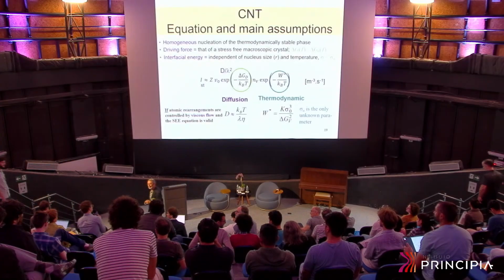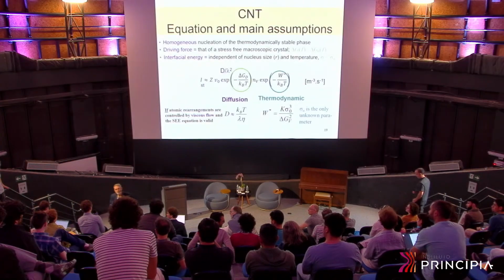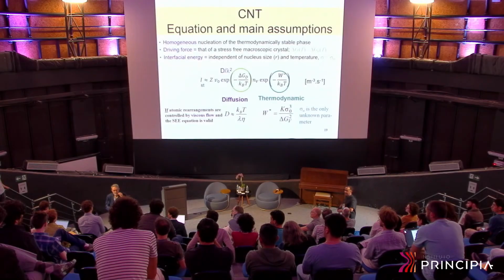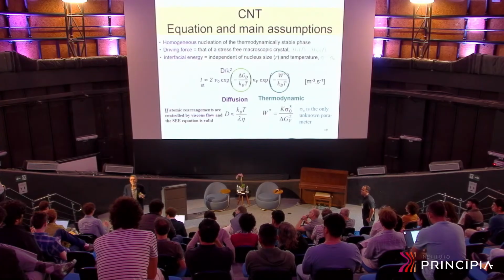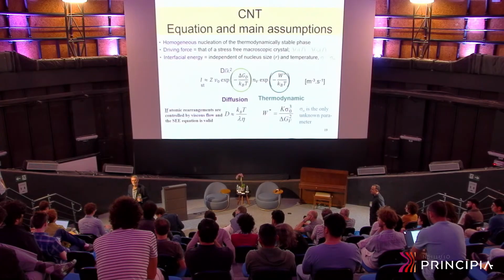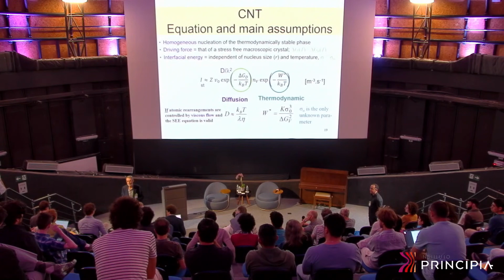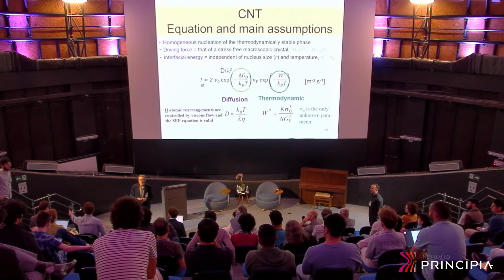Is there a known theory for the temperature dependence of the interfacial energy? Yes, there are empirical models that predict a positive temperature dependence for the interfacial energy. I'm sorry for not showing that, but yes, and they agree. Very good question.